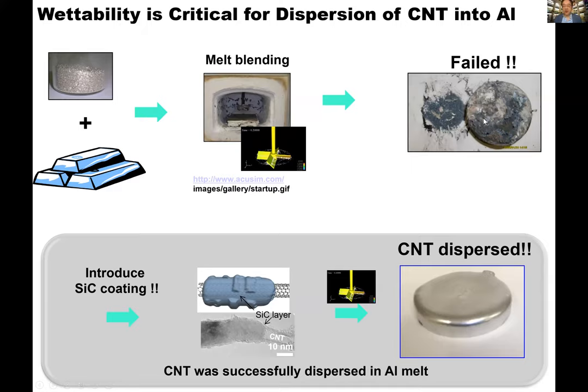Carbon nanotube actually doesn't wet metals very well. So if you just put it inside, it just floats on top and you don't get good dispersion. But by using different ways, we're able to change the wetting angle between the carbon nanotube and the molten aluminum. So this red is the molten aluminum. This is an impeller. And at some point, we're going to put in something called the master alloy. So this is pre-mixed ball milled carbon nanotube with some aluminum in it. And then there's an accelerate. So initially, you see this, but eventually you're able to disperse these one-dimensional tubes into the molten aluminum.